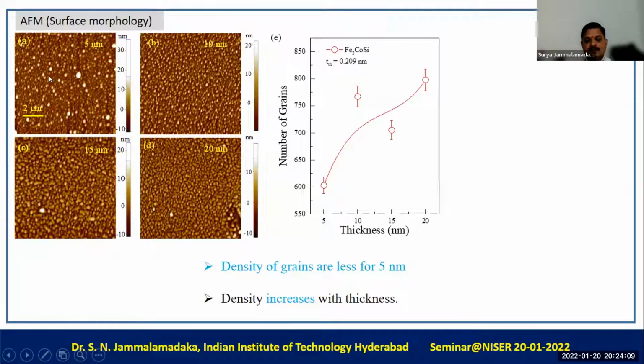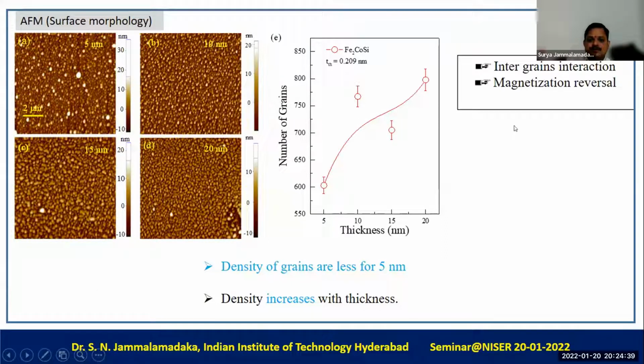So in order to understand the morphological studies, we have done atomic force microscopic studies. As you can see here, from 5 nanometers to 20 nanometers, the uniformity of the film has increased. Essentially, at 5 nanometers the density of the magnetic grains is less, and at 20 nanometers the density is very high. So as a result of the difference in the density of the grains, it may so happen that the